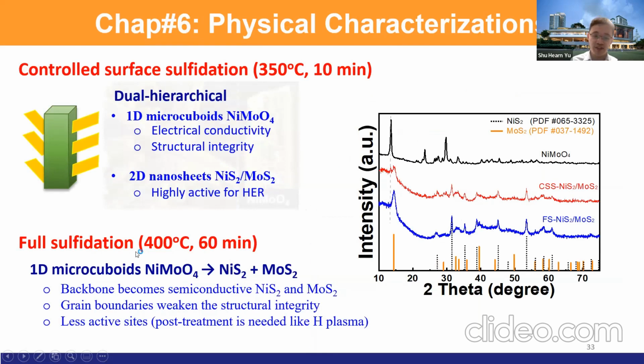Now, if you perform full surface sulfurization, you can do it at 400 degrees C for 60 minutes, and then you will fully form nickel sulfide and molybdenum sulfide. The nickel molybdenum oxide, in this case, will be fully converted. However, if you perform controlled surface sulfurization, the microcuboid nickel molybdenum oxide still serves as the support, the backbone. This material is conductive. However, MoS2 is not conductive. So we want to have a conductive skeleton to support our catalyst. So this is very important.